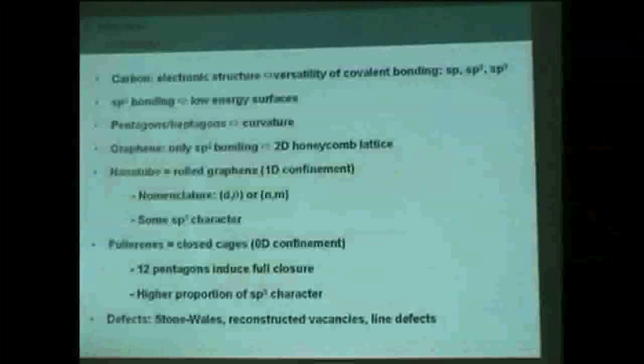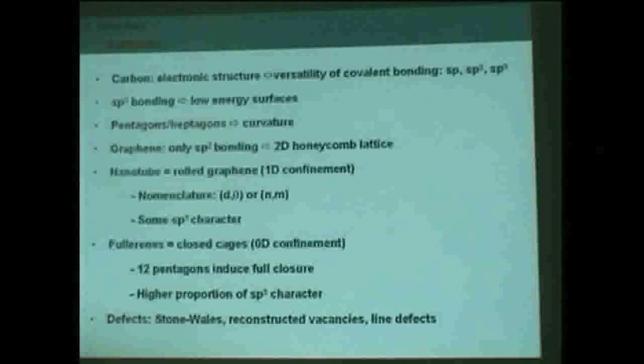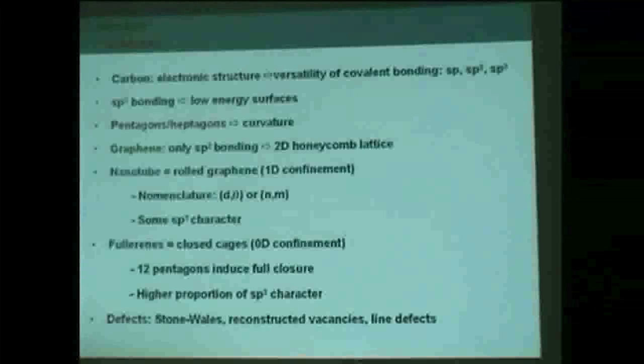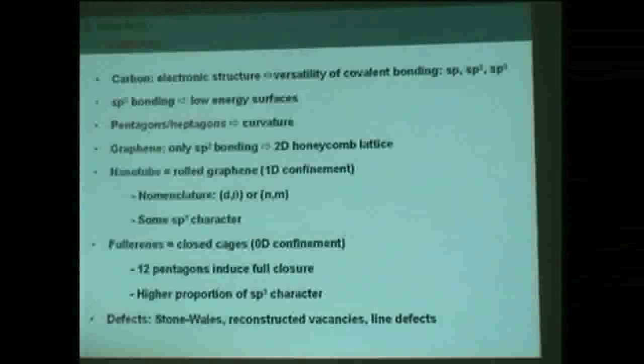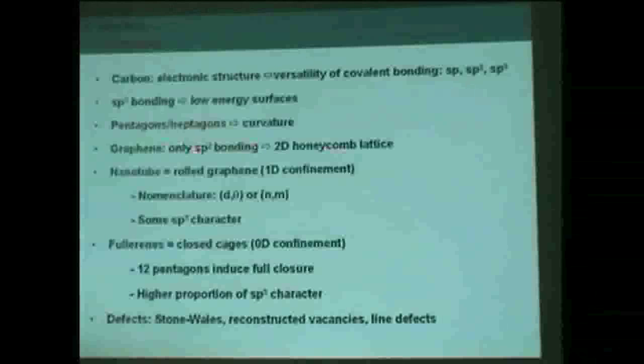Okay, so I will make a summary of what I said quickly. You can read that. So carbon can make sp2 bonding, which makes something flat, but you can also put some sp3 to have it curved. You can have pentagons and heptagons added in the structure to create even higher local curvature, Gaussian curvature. The three types of carbon nanostructures we have been going through are graphene, purely sp2, flat; nanotubes, which is rolled graphene, with this one-dimensional symmetry, a cylindrical symmetry.